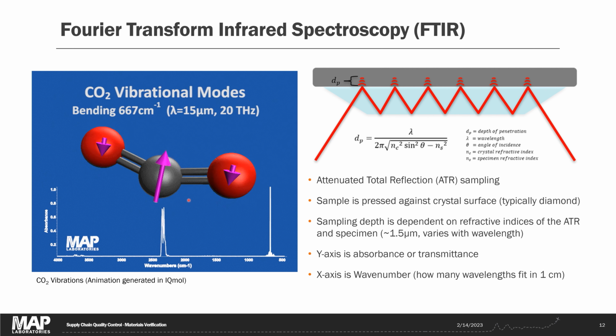And a little bit more on the ATR sampling mode. So this is our diamond optic here. We have an infrared beam bouncing through the diamond optic using total internal reflection. There's a small evanescent wave that extends out into the sample, and that's where your absorbance is occurring for your spectroscopy. There's an equation for the depth of penetration. It actually varies across the spectrum, but it's roughly about 1.5 microns or so. We're sampling a little bit thinner on this side and a little bit deeper on this side.